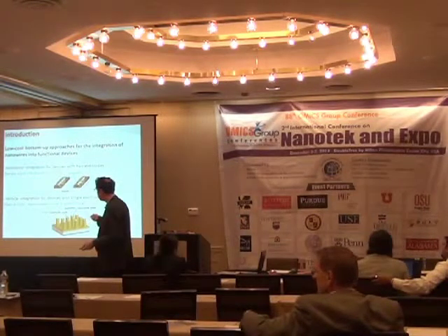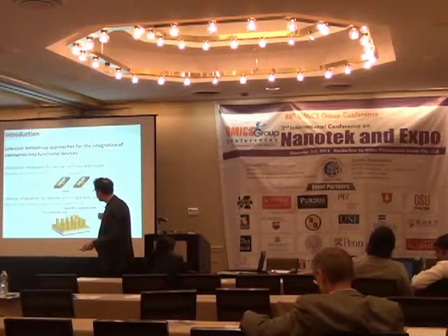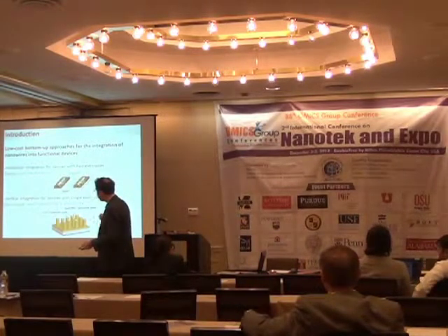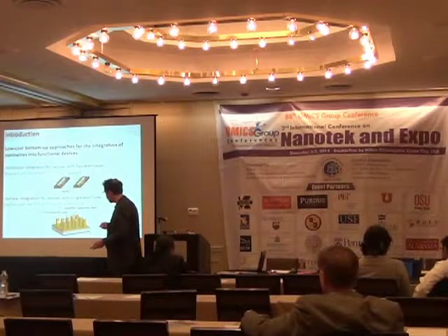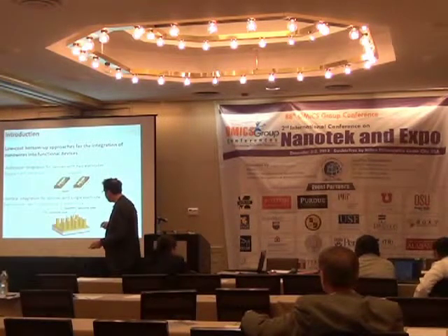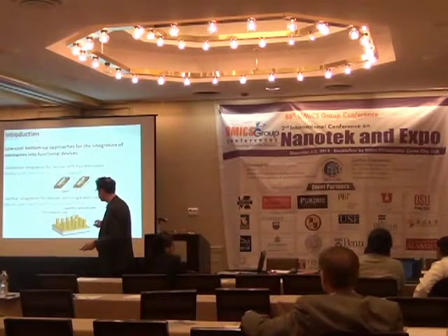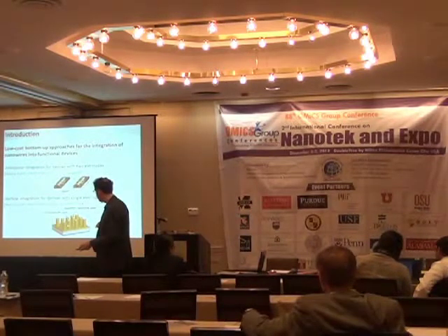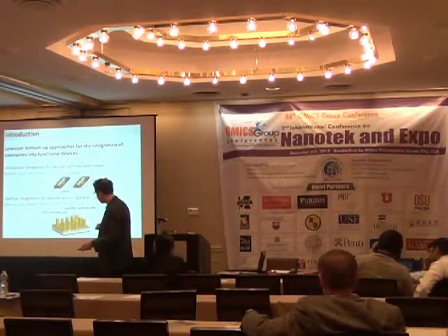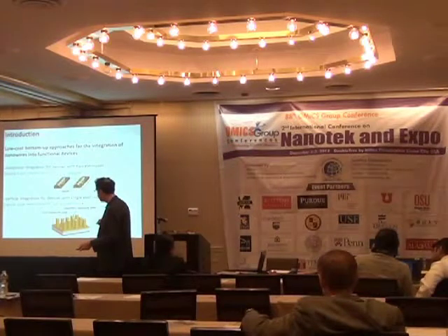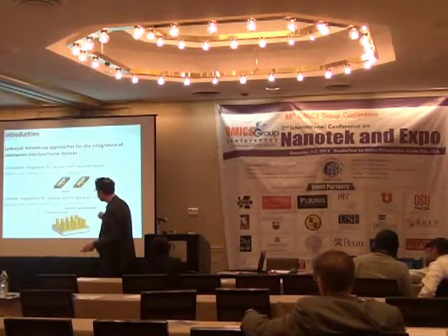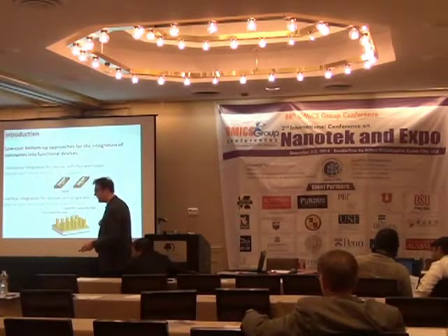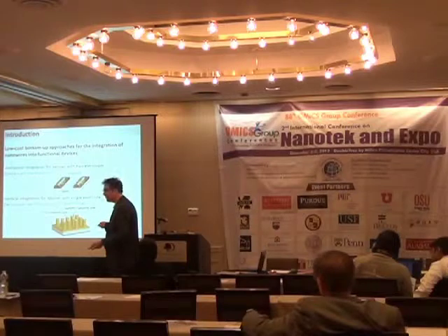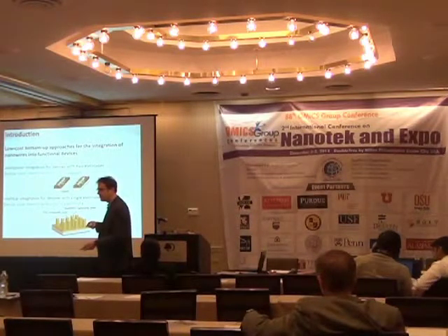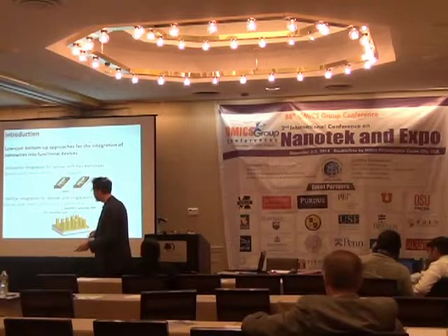And the second example, I call that horizontal integration. So we get the nanowire in the same plane as the quartz substrate. And the second example is the vertical integration devices, where you have vertically aligned nanowires like that. In that case, the plus and minus that you need are up there because the nanowires are connected at the bottom. The connection to the nanowires is made with an electrolyte. So this is basically a sensor that can't work in air, and that needs an electrolyte. And I use that to split water, to generate hydrogen from water.